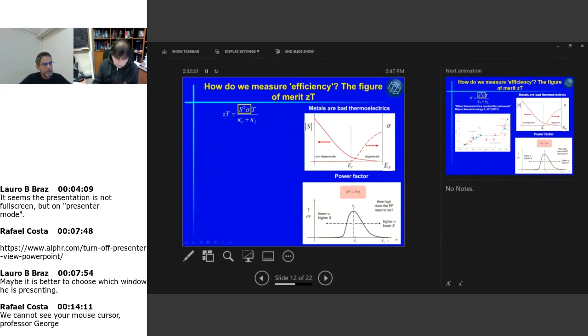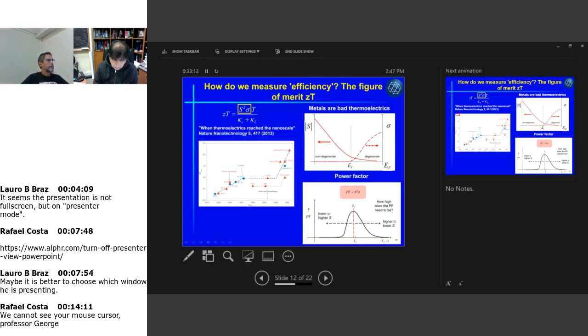So that's the region where you want to be with doping, or with your chemical potential. Let's call the Fermi energy the chemical potential. There you have a balance where the Seebeck coefficient is not too low yet, and the conductivity has already increased a little bit. So that's where you want to be for the figure of merit ZT to have a value where your system can be used in applications.